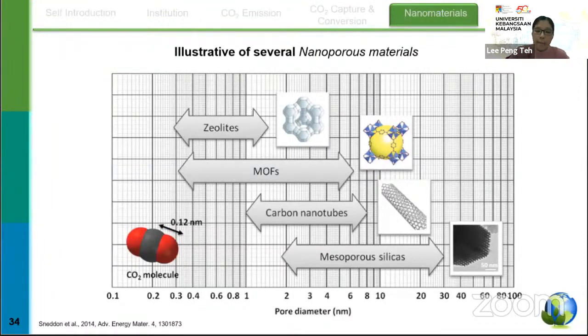We have also metal organic framework. In a metal organic framework, we have a combination of metal and also organics as the ligands. For example, we have copper MOF, cobalt MOF, and so on. MOF materials attract very good interest in CO2 capture and conversion. This is because with MOFs we can easily tune the pore and the nature of the MOFs based on different synthesis approaches. And MOFs have a significantly high surface area, so they act as very good adsorbents.